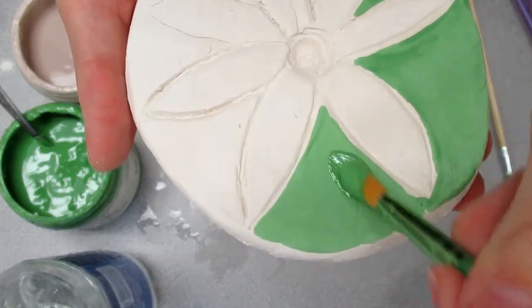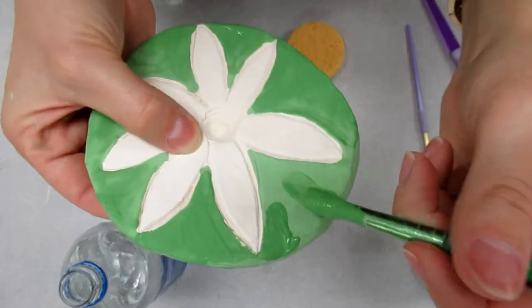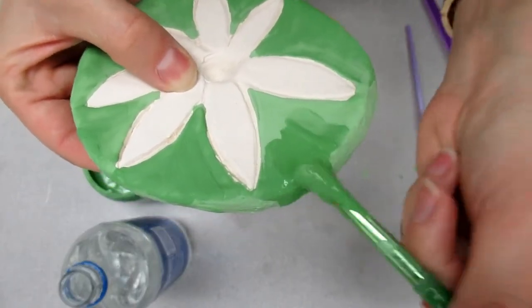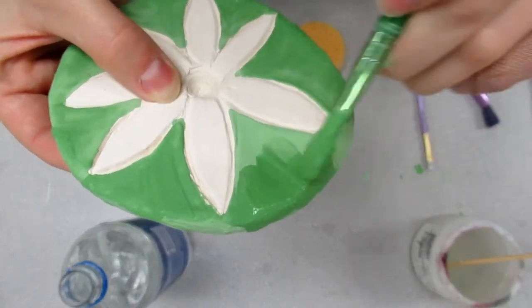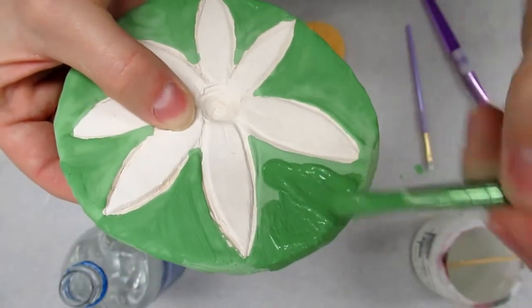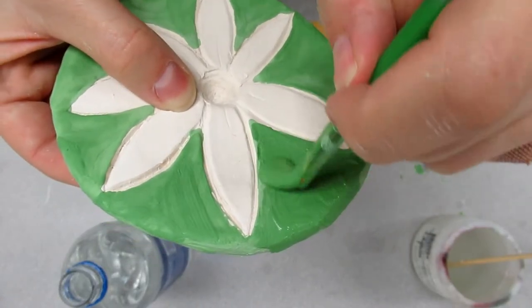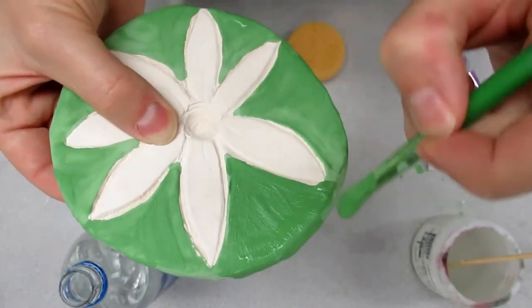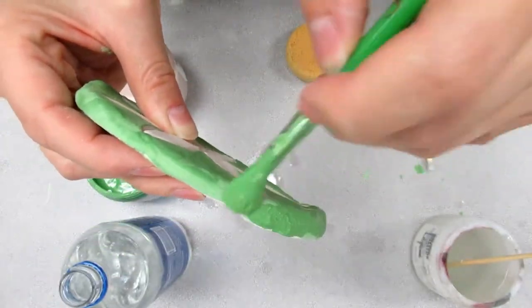The challenge is to keep track of where you have painted once and where you have painted twice. Don't over-glaze! More than two coats, or a glaze applied much too thickly, will run off your piece in the kiln and drip onto the kiln shelves. Also try to brush smoothly and without air pockets, because these can become pinhole bubbles and bare patches when the glaze liquefies in a firing. Always apply your glaze layer even and smooth.